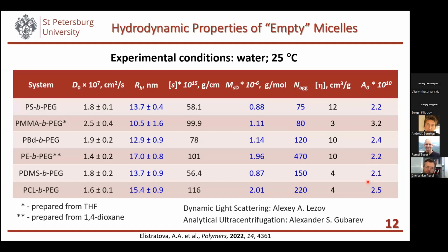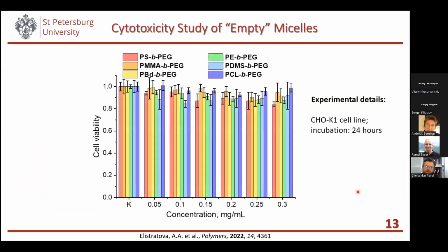So all the hydrodynamic data tell us that we deal with spherical compact nanoparticles. Then we investigated the cytotoxicity of empty micelles, and we could show that they are non-toxic, especially those based on caprolactone, which is a biodegradable and biocompatible block.